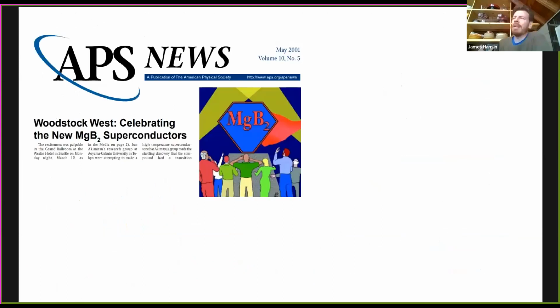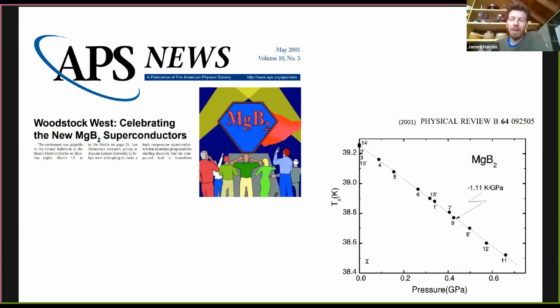So the very first thing I did in my career in high pressure was to study the pressure dependence of magnesium diboride. This material was reported with a lot of fanfare, and I think there was a lot of excitement that maybe there would be other related materials, that it would be possible to raise TC. It turns out that no matter what you do to MgB2, TC goes down. So here's a result from one of my first papers where we showed that TC goes down under pressure. Subsequent studies found the same thing.